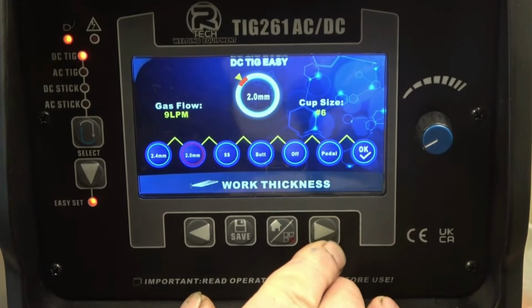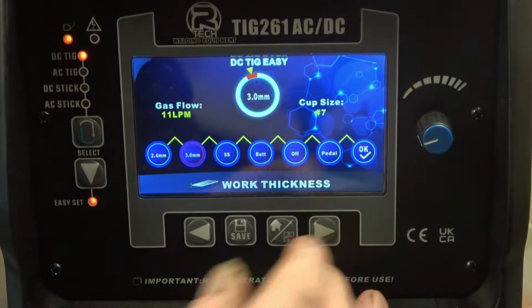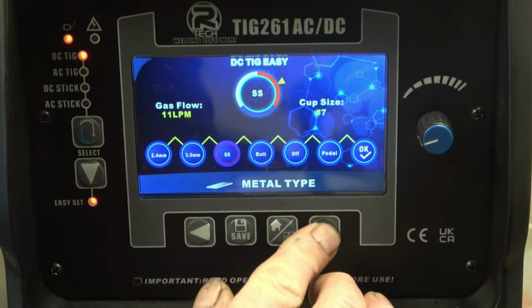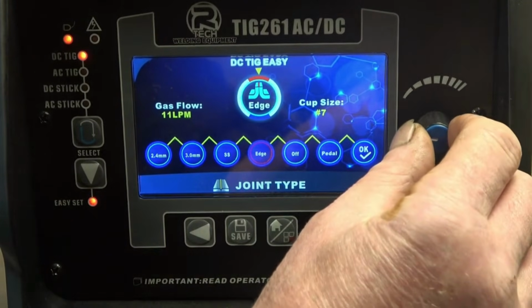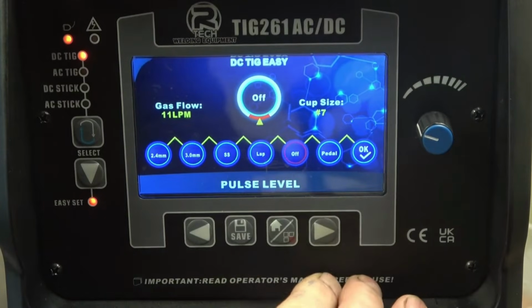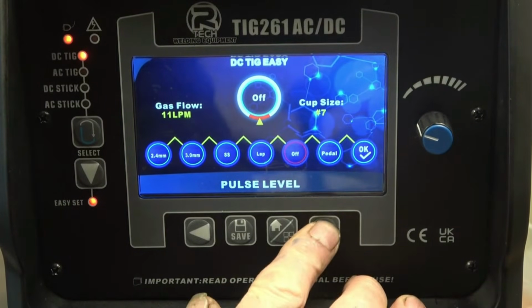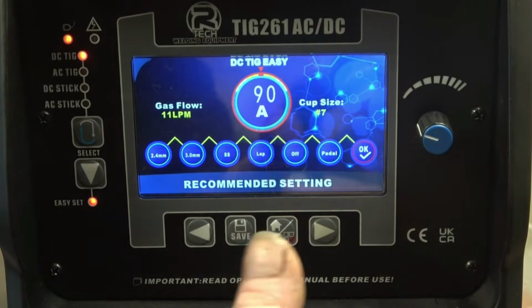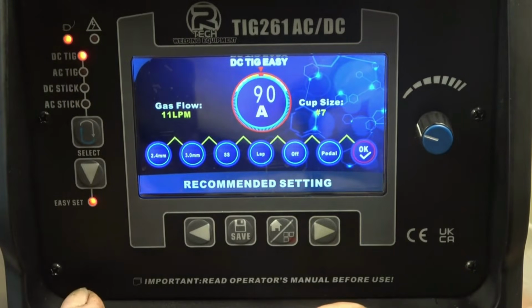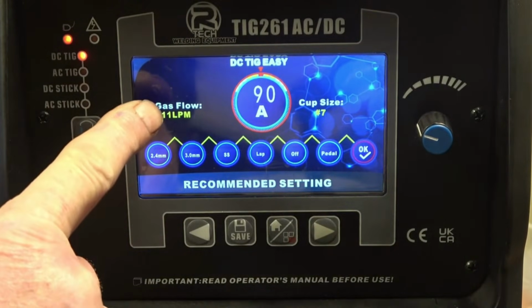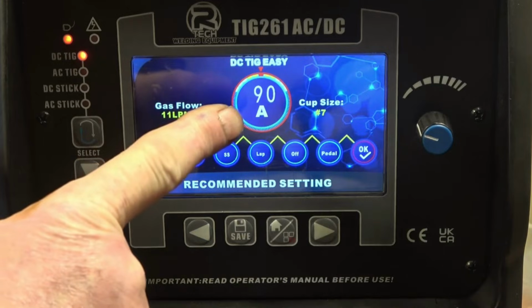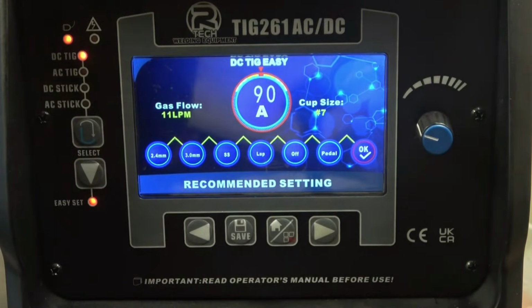We're going to go up a thickness now. Still a 2.4 tungsten. Going to go up to 3mm stainless steel, and we'll do a lap joint. Pulse is off, on a pedal. Okay, simple as that. So it's 11 litres per minute argon. It's going to give a 90 amp starting point with a cup size number 7.